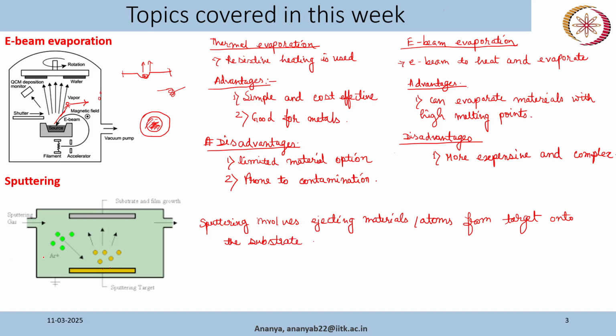So for sputtering, we normally use argon or any other suitable inert gas. That is because we don't want any contamination in our target or in our film. That is why we use argon, and also the reason is that we want to eject atoms from the target. So we want an inert gas that has an atomic weight close to the target material. In most cases argon works, and if it is a very light material, then neon is used as a sputtering gas, and if it is a very heavy element, then we use krypton or xenon as the sputtering gas.